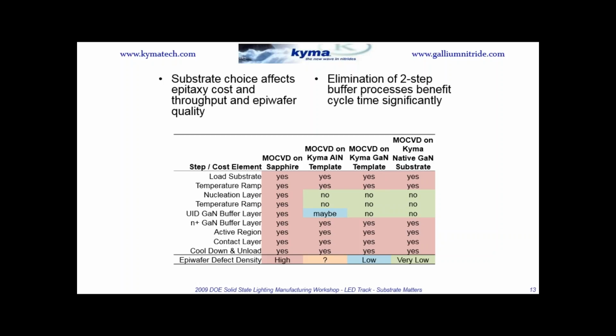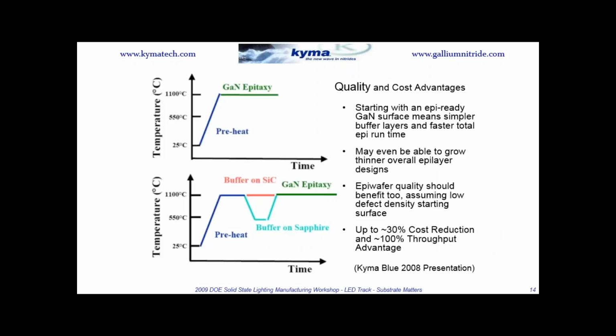And it turns out that, for instance, for LED manufacturing facilities, half of their capital equipment is spent on the MOCVD tools, and those MOCVD tools, about half of their growth cycle for making an LED is spent on buffer layers. That's really expensive stuff. So, Kyma and others feel like we can give you the buffer layer cheap and at an even higher quality. This one is again showing how you can reduce the cycle time by growing on a GaN substrate on the top.